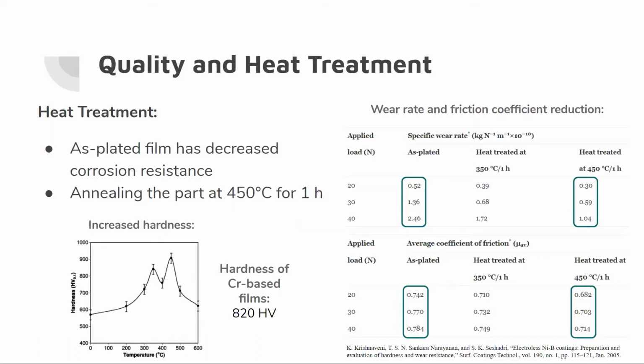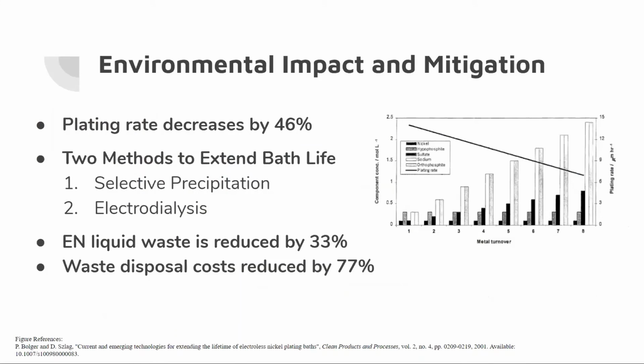And now we will do the environmental impact and mitigation analysis. Thank you, Dayan. To address our design criteria to minimize the environmental impact, we introduce a treatment of the spent plating bath to the manufacturing process to extend the bath life. As shown in the graph, over time, there's accumulation of byproduct species that significantly reduces the plating rate by 46%. This will result in the bath needing to be disposed of.